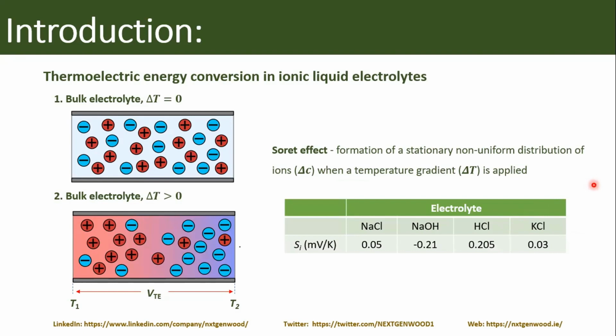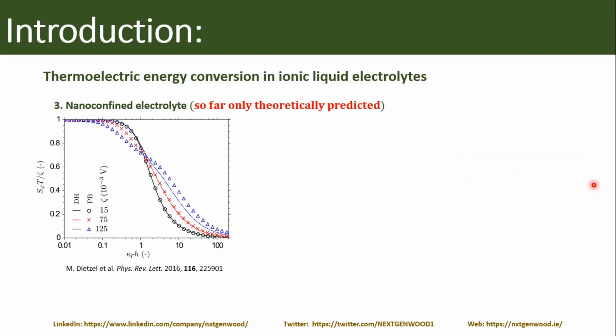And if we look in the literature for bulk electrolytes, this Seebeck coefficient, which is of course not really a Seebeck coefficient, but we can call it like this, is quite small and normally less than a millivolt per Kelvin. So of course, this is not enough to make an effective device, and we want to increase this. And so we decided to look for a way to do that. And one of our partners recently found it theoretically. So what I've shown you right now is just a theoretical prediction, which is not proven experimentally yet.